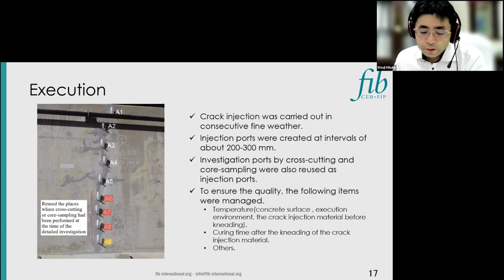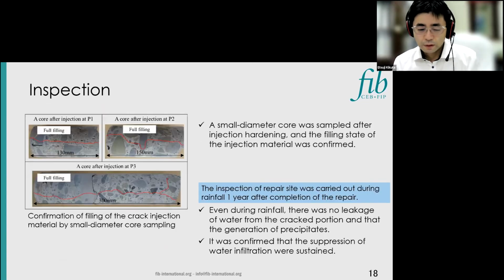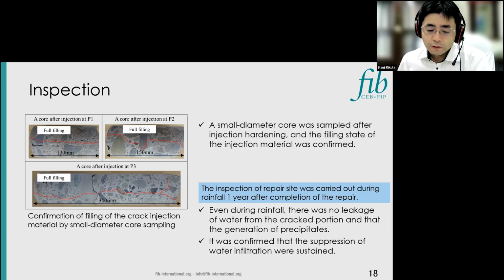In order to ensure the quality, the following items were managed. Management of temperature and curing time is especially important. About the inspection after execution. Since the cross-cutting method had little execution record at that time, small diameter cores were taken after injection curing, and the filling state of the injection materials was confirmed. As shown in the photograph, injection materials had completely filled the cracks as far as the eye can see.